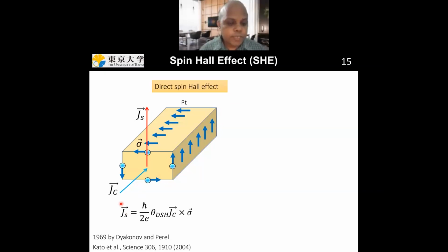The spin Hall effect was theoretically proposed in 1969 by Dyakonov and Perel. It was only experimentally realized in the year 2004 because it is a very difficult experiment. It took almost 35 years to realize this experimentally. So what is spin Hall effect? Suppose you take a bulk piece of metal, for example platinum, and pass current through it. Then you can create spin accumulation on the surface. During this process, you create a spin current, which will be mutually orthogonal to the charge current direction and spin polarization direction, and whose magnitude will be given by this expression over here, where theta is called the spin Hall angle.